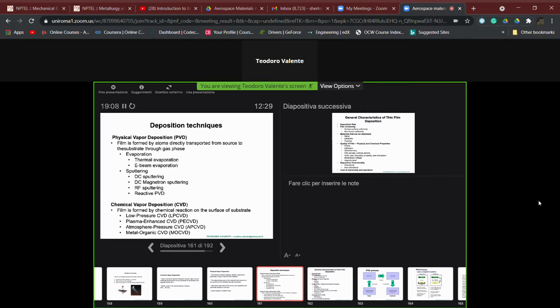What does it mean? It means that atoms are put in the gas phase by sputtering, for example. Then they can meet an atmosphere with a special composition. Think again, just to have a reference, titanium and nitrogen. This atmosphere can react with the atoms in the gas phase and form, for example, titanium nitride. And in this case, we will have the fabrication of titanium nitride coatings, which has a composition different from the initial bulk materials from which we have generated the atoms or molecules which will then be deposited.